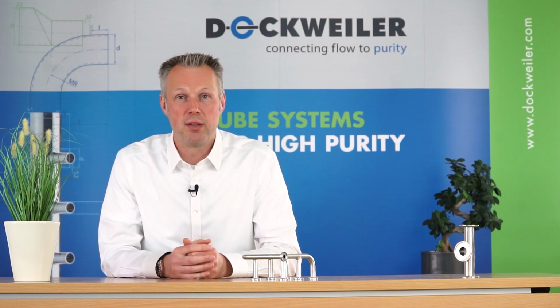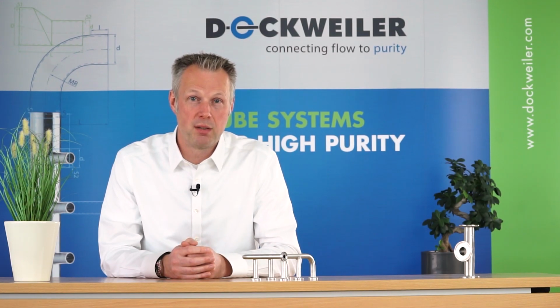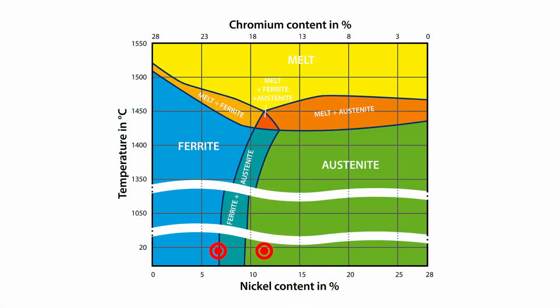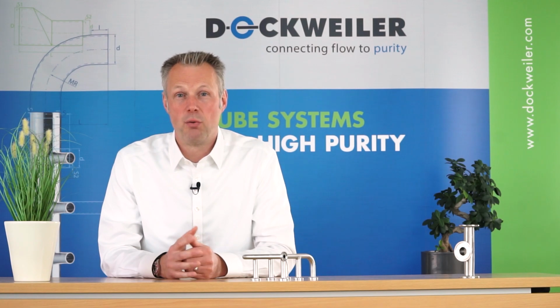And this is what you do with solution annealing. During solution annealing, you elevate the temperature roughly up to 1040 °C, which is low enough to maintain the mechanical stability, but high enough to help the atoms to move, so that the ferritic crystals will be dissolved in the austenitic crystals or in the austenitic structure. This is what is done during solution annealing.